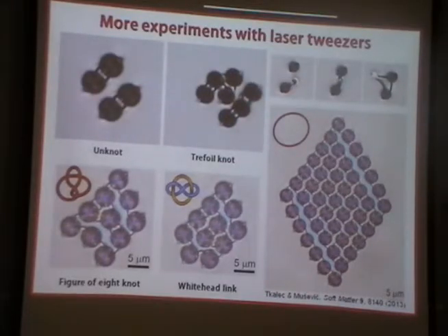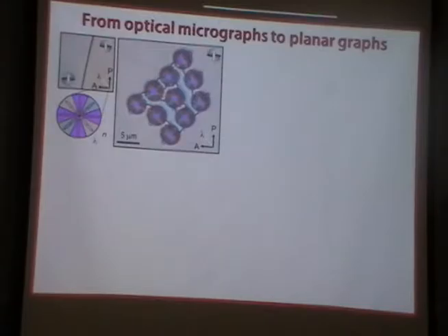So you might also ask why we see these colors here and what they mean. These are just differently oriented twisted nematic domains. If you look at the nematic between crossed polarizers with an inserted optical retardation plate, you can distinguish these two different perpendicular orientations under the microscope, so they appear in two different colors. And wherever you cross the disclination line, this minus 1/2 disclination, the orientation of the molecules turns by 90 degrees.